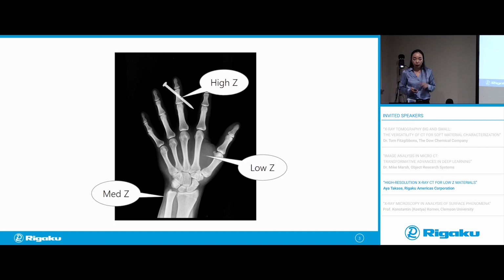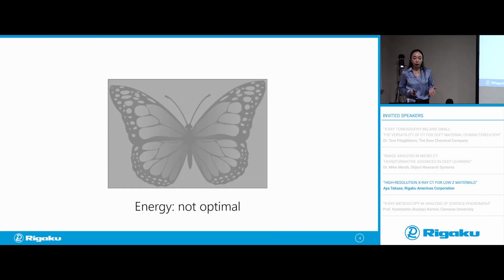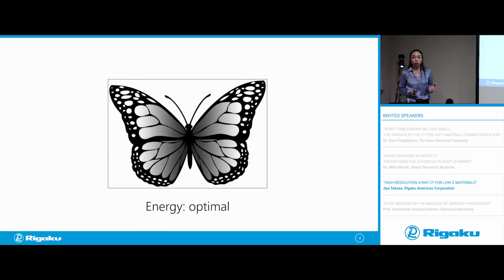So one of the key things to remember when you image low Z materials is that when your X-ray energy is not optimal, you don't get a lot of good contrast. You have to optimize the X-ray energy to increase the contrast and increase the image quality.